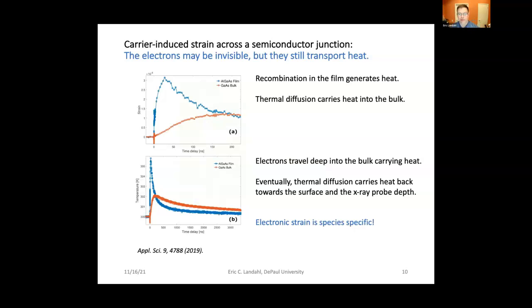And to check it, there's a control built into the experiment, which is that those initial electrons created that pass through the junction will eventually generate heat deep in the bulk material. And that's evidence you can see in this first set of strain curves. So this is again the peak shift. This is strain measured from the diffraction, and over the first 200 nanoseconds, this is the rapid transient as the impulsive strain goes. But then we're seeing heat being generated up here to 20 nanoseconds or so inside the film, and then it's starting to diffuse into the bulk material, which then correspondingly raises in temperature.